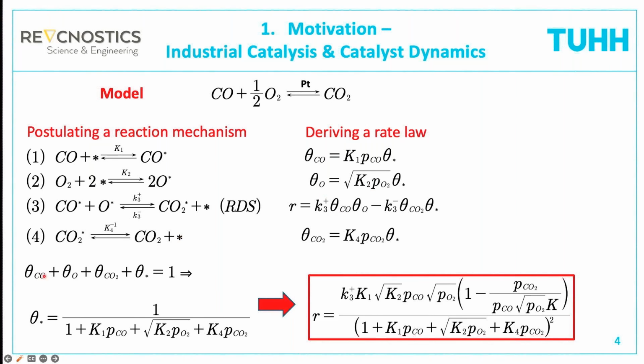And what we then do is also a strong simplification. We assume that the catalyst is static. So the number and type of active sites is constant and doesn't change. And then we invoke site conservation. So we say that the site is either covered with CO, with oxygen, with CO2, or it's free. And when we do this, we can derive an analytical expression for the fraction of empty sites. Then we plug this all in, and we get a rate law, which is called the Langmuir-Hinshelwood-Hougen-Watson type rate expression.